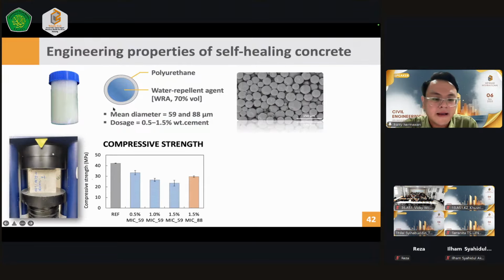So what will be the effect of the microcapsules? Well, the use of the microcapsules will induce a strength decline, or a reduction of the compressive strength. If you see here, by increasing the amount of microcapsules from 0.5 up to 1.5%, there will be a gradual strength reduction with increasing capsule dosage. But why is the strength being decreased?